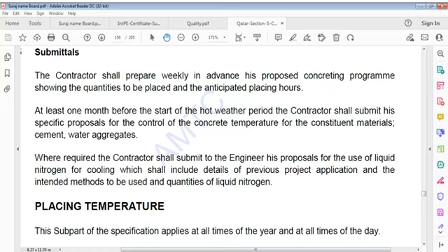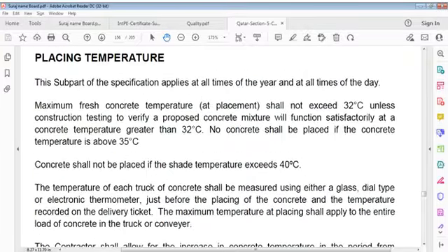Placing temperatures. This part of specification applies at all times of year and at all times of day. Maximum fresh concrete temperature at placement shall not exceed 32 degrees Celsius unless construction testing verifies a proposed concrete mixture functions satisfactorily at a concrete temperature greater than 32 degrees Celsius. No concrete shall be placed if concrete temperature exceeds 35 degrees. Concrete shall not be placed if shade temperature exceeds 40 degrees Celsius.